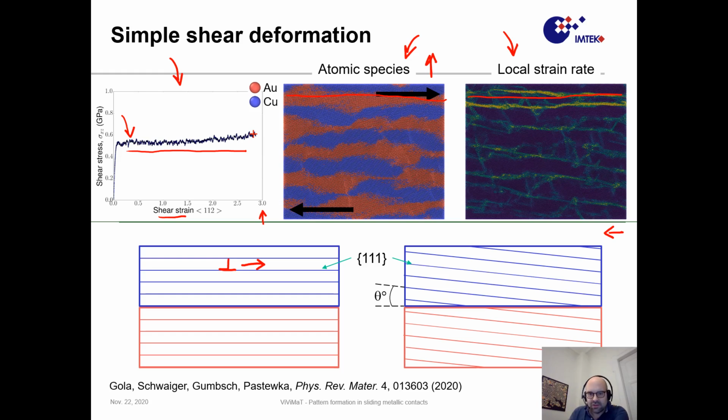If we have this tilted lattice, then a dislocation here that moves on the 111 plane will eventually hit the interface, and of course at the interface the lattice constant changes, and in this case the interface is a little more complicated. There's lots of defects at the interface, so there are obstacles that hinder the motion of the dislocation. And this essentially hardens the material. The dislocation gets stuck at the interface, and then the system needs to react with something else. What it will do is start creating a slip plane that sits on another 111 system that's not aligned with the interface.